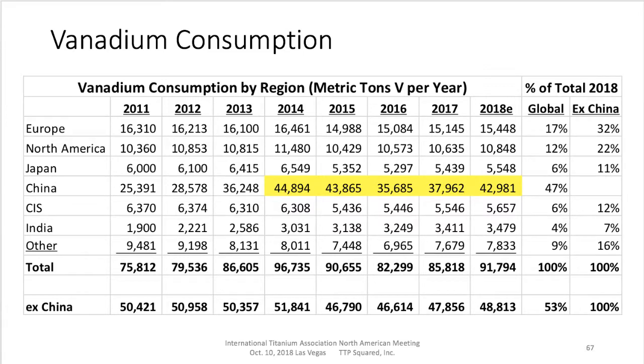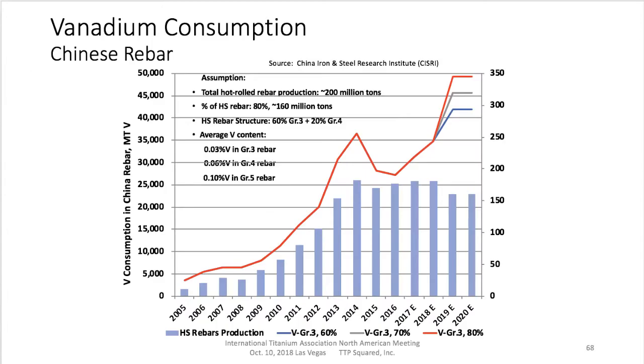So what happened? What we discovered was that in 2015, vanadium consumption in high-strength rebar in China dropped precipitously, while the actual production of high-strength rebar was fairly stable. An investigation discovered that there were a lot of very small induction melting steel operations in China generating poor quality billets. They can't control the sulfur or the phos. So poor quality steel was being rolled, quench and tempered, and sent out into the field as grade 3 rebar. Grade 3 rebar requires high yield strength, 350 megapascal yield strength minimum, and it also requires good elongation properties, with an ultimate to yield strength ratio minimum of 1.25. And it's critical when you have this steel working in seismic activity.